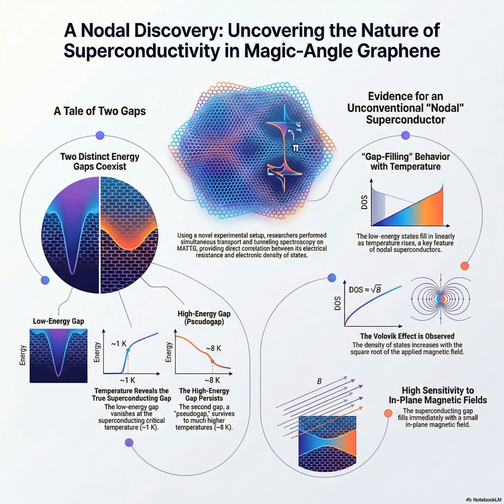So any slight difference in the twist angle, or even a tiny defect on one flake versus the other, throws the whole thing off. It meant the data wouldn't correlate perfectly. You couldn't definitively say the energy gap we see here is what causes the zero resistance we measure over there. It created this fundamental ambiguity. So they had to solve the device problem first.